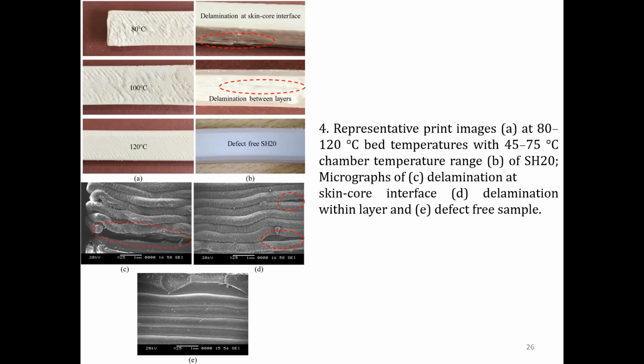So the uniform and same texture on the bottom and uppermost layers of the printed samples is very crucial to render a similar stress state under a given applied load. If the stress distribution is non-uniform, then that is the region wherein the crack initiates, wherein there is a high stress concentration, and the material fails earlier and its load carrying capacity drops drastically. So this we need to take into account when we are designing an experiment, when we are designing the material system, and ultimately when we are processing it. And that's how we took the help of finite element simulation.